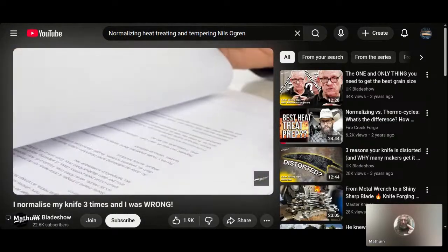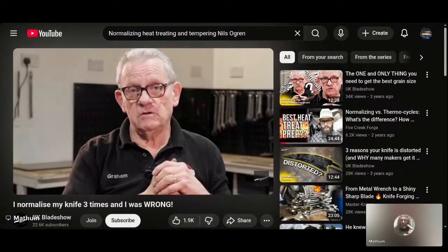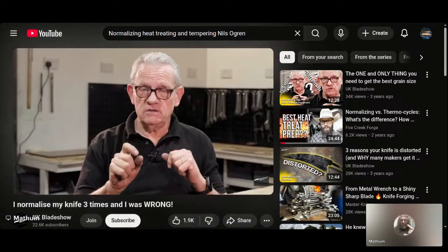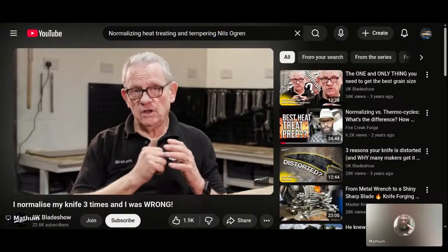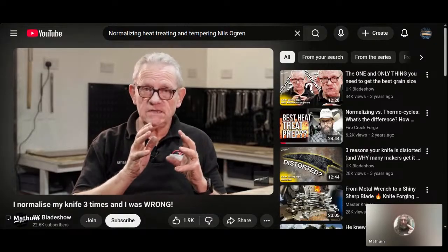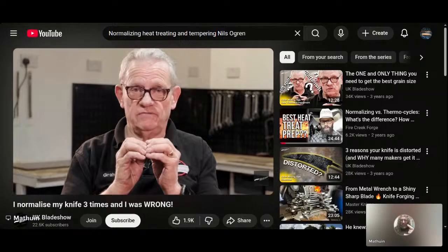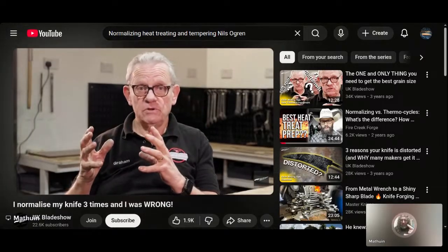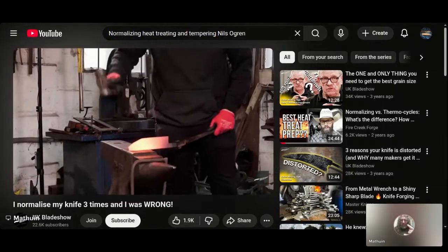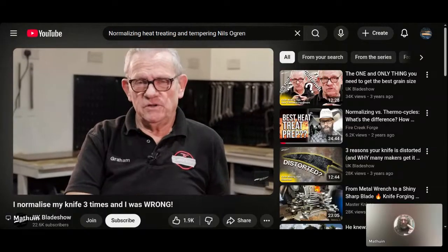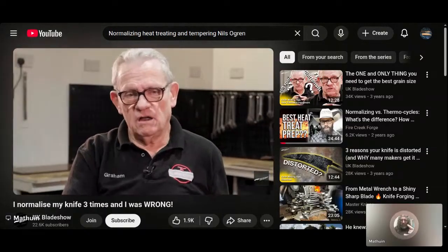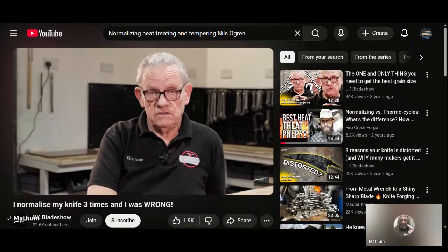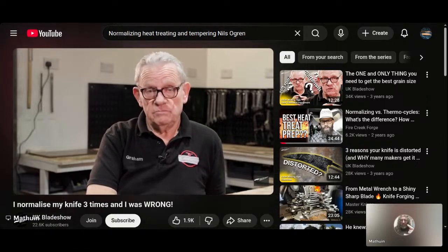If you take an industrial spec on a piece of steel, it will actually give you a grain size that material should be when you come to heat treat it. I'm not going to bore you with the technical detail, but there's a specific size the grains have to be. And if they're too big, then your metal becomes brittle. And I'm sure a lot of you who are blacksmiths will know that, I've heard people say, oh, it's just an occupational risk of blacksmithing, or when you come to harden it, sometimes they crack. If your grain size is too big, they will crack. So you need to normalize it properly.